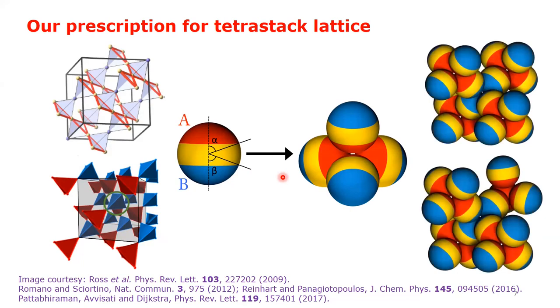The crystal structure prediction confirms that such designer building blocks can indeed stabilize both the cubic and the hexagonal polymorphs, which are of equal energies on the crystal energy landscape.